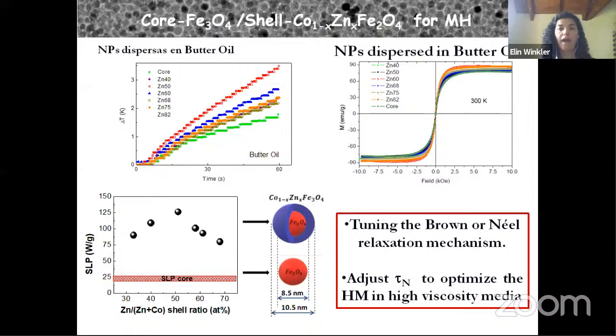So, which is important here: in this way, by the core-shell nanostructure, we can tune the Brown or Neel relaxation mechanism, and also we can adjust the Neel relaxation to optimize the magnetic hyperthermia in high viscosity media.